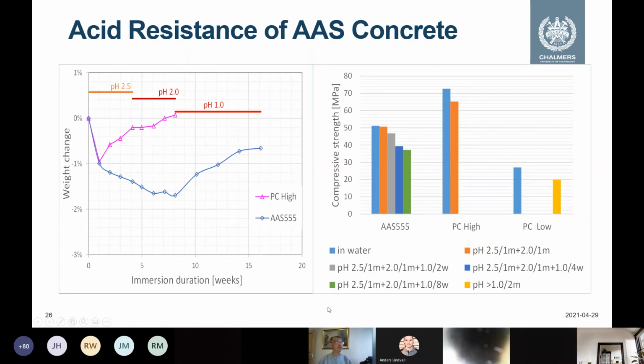So we tried to test concrete. For concrete, based on our previous experience, we directly put pH 2.5. After 1 month, we found that the weight loss is not enough. It is just 1%. So we decreased the pH to 2. So after 1 month more, meaning 2 months under this pH between 2 and 2.5, we directly measured the strength. So you can see that after 2 months for alkali-activated concretes, there is almost no strength loss. So that keeps a similar strength.